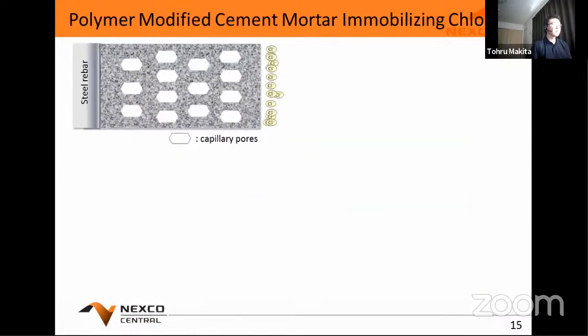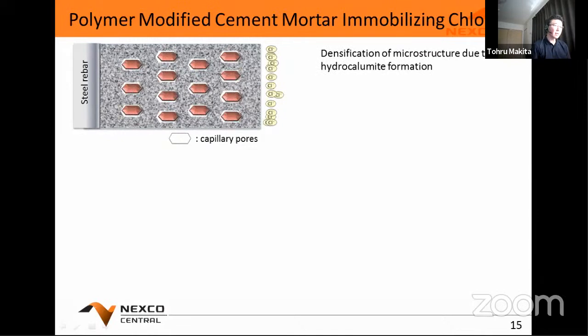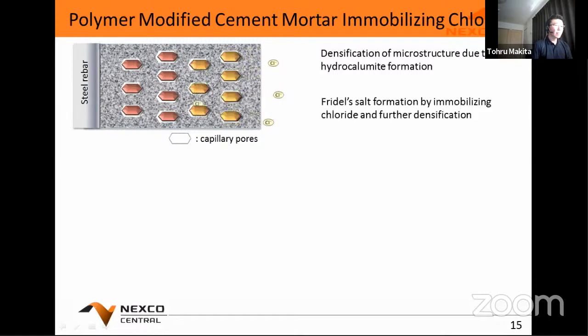So at first, free water exists in capillary pores of repair mortar. And calcium aluminate reacts with free water, and hydrocalumite is produced in capillary pores. As a result, the microstructure of repair mortar is densified. Afterwards, chloride ions enter the repair mortar, and hydrocalumite reacts with chloride, and Friedel's salt is formed, which means chlorides are immobilized, and further densification of the microstructure occurs.